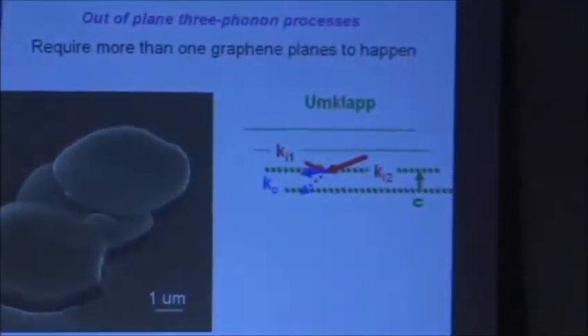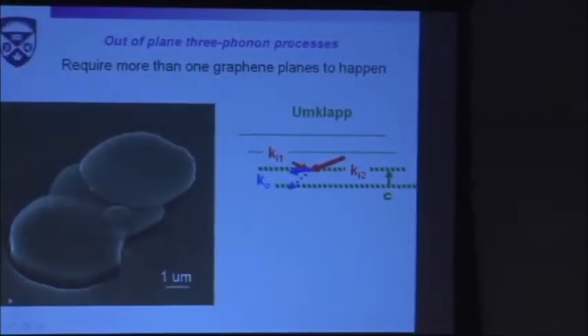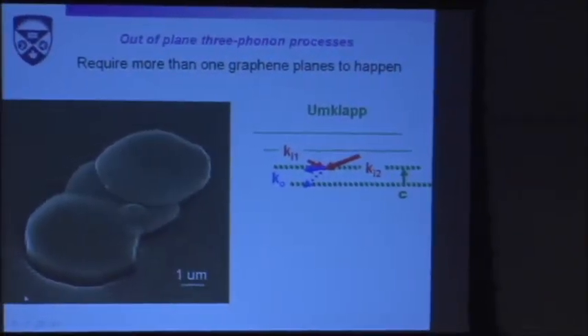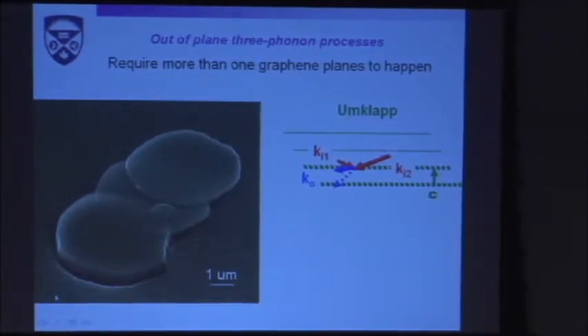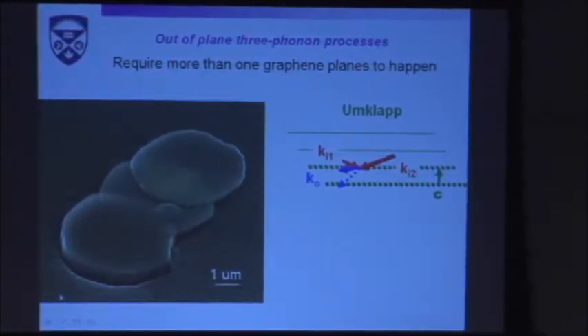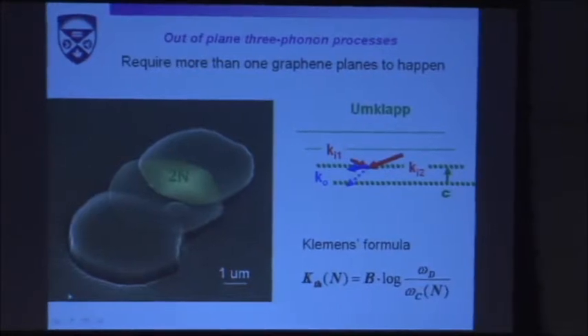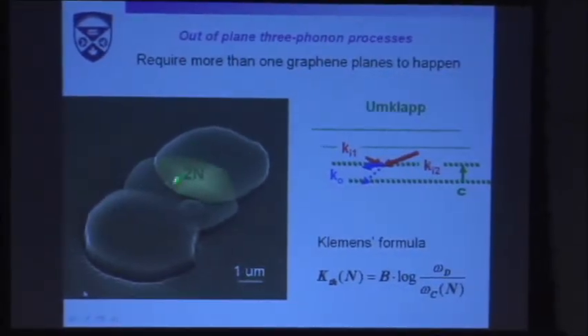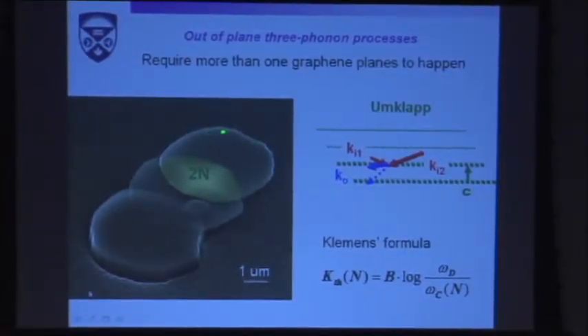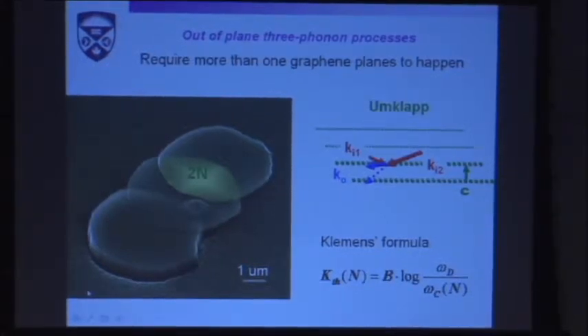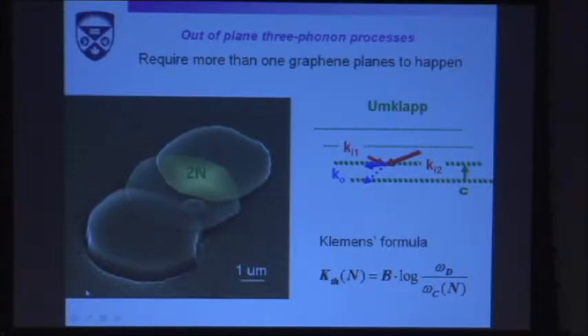So you're scattering your phonon excitation to another layer. Of course, you need to have that other layer. If you have graphene, you have just one layer, and these processes are forbidden. And you have to go to the fifth order and so on. So the areas where you have 2n layers, where n is the number of layers in the individual graphene flake, are the ones that limit the thermal conductivity of graphene.